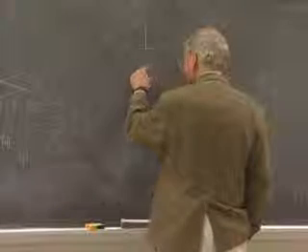Okay, so the interesting thing about this surface is that if you decided to pick up a random fragment of crystal and determine what its piezoelectric modulus is, one way of doing this, a poor man's test for piezoelectricity, is to just clamp a fragment of crystal between two electrodes and then hook this up to a variable frequency generator that sweeps through a range of frequencies, changes the frequency of a voltage across these plates, and then comes back and sweeps again.